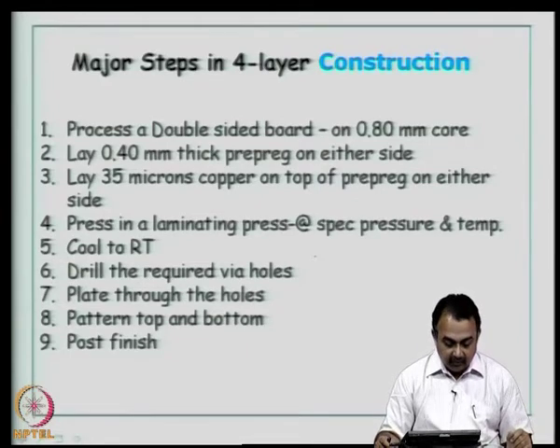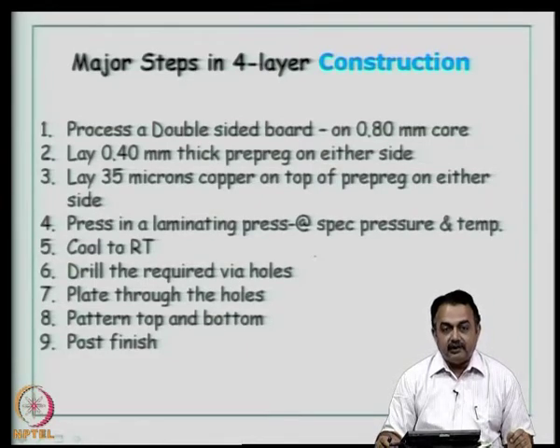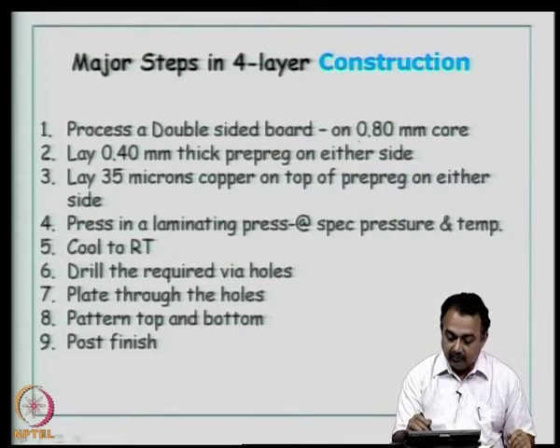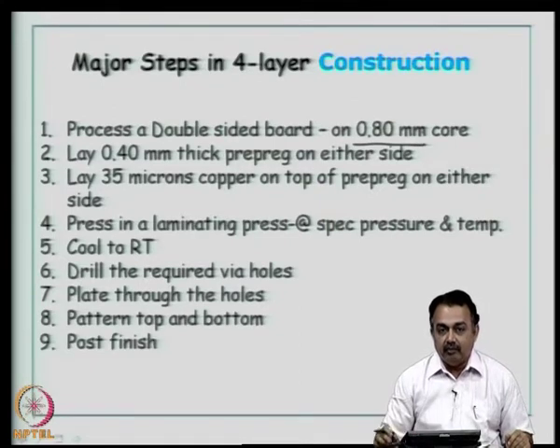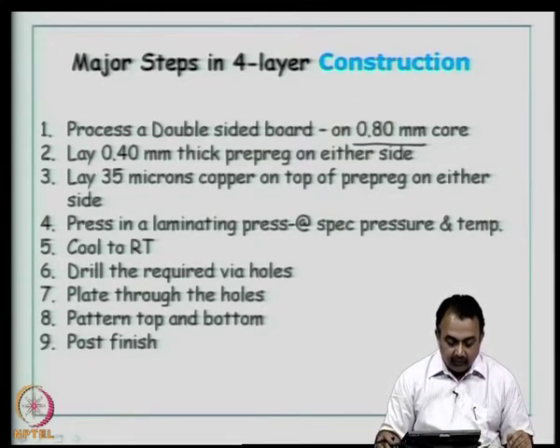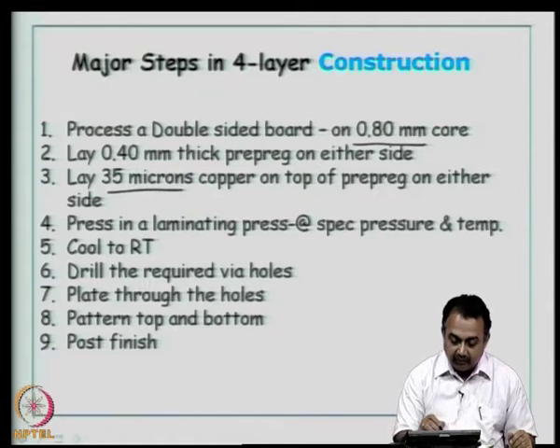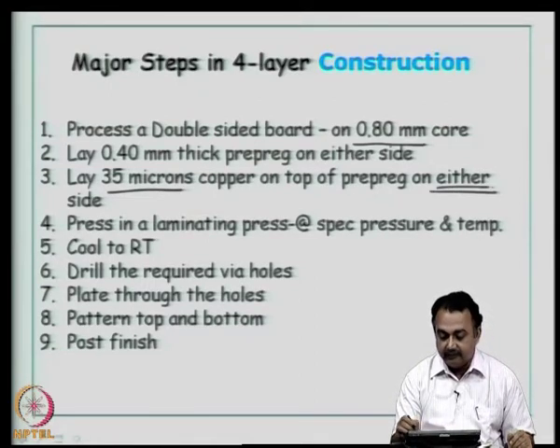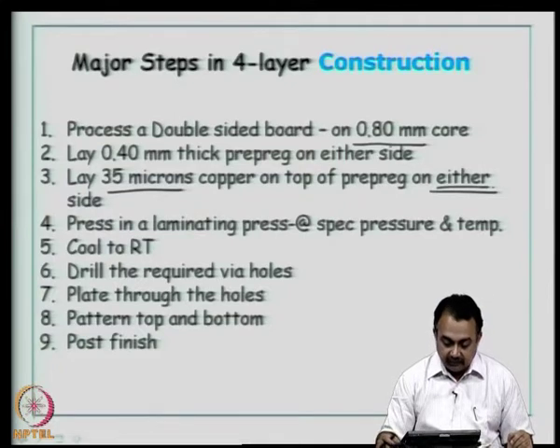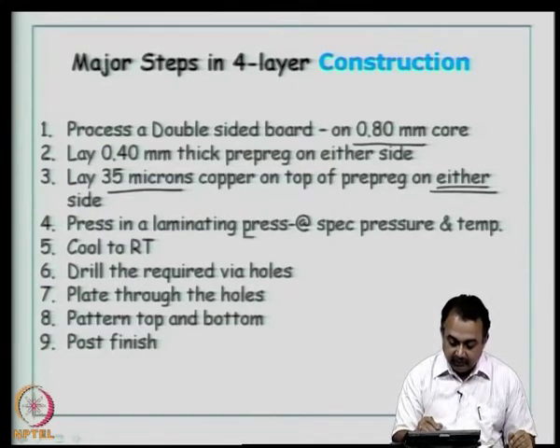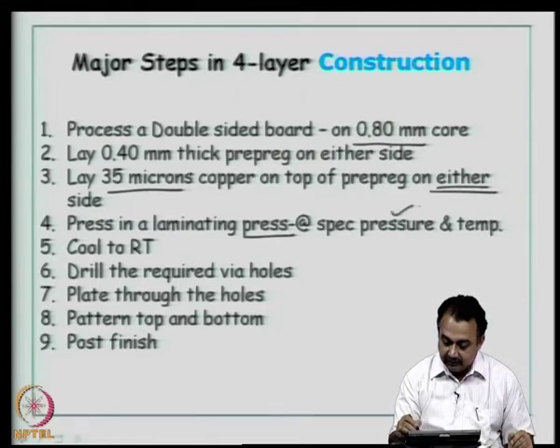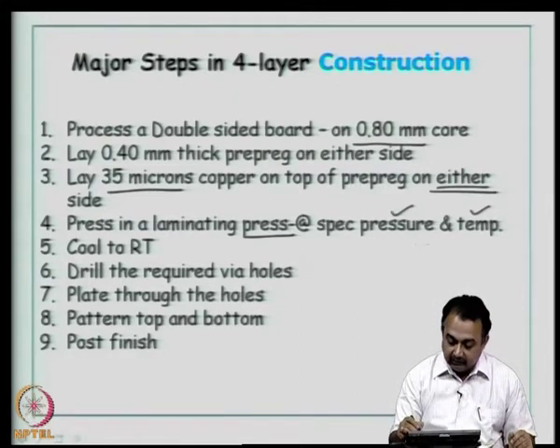So, in a nutshell, what are the major steps in creating a 4-layer board? Process a double sided board or, let us say, 0.8 mm core. Your starting double sided board will be 0.8 mm. Now, you lay a 0.4 mm thick pre-preg on either side, right. So, it is almost 1.6 mm thickness now. Then you add 35 microns of copper on top of the pre-preg on either side. So, that completes the copper construction. Introduce it into a lamination press, specified pressure and temperature. It is a very slow process.